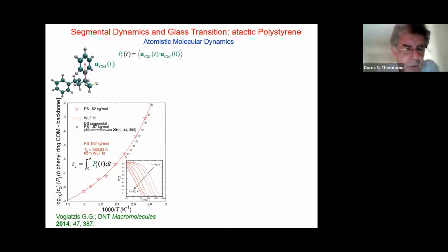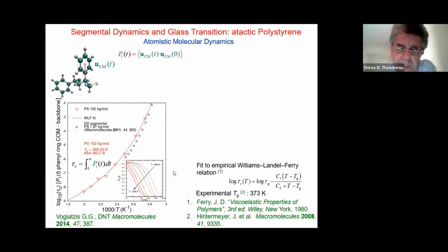Now, this kind of dependence, this nonlinear dependence, is very frequently described by a Williams-Landel-Ferry or a Vogel-Fulcher-Tammann expression relating the relaxation time with the temperature. So if one fits this line that comes out of the molecular dynamics simulation with this WLF relation, one can extract an estimate of the glass temperature, and here it is, roughly 380, which is not very bad when one compares it to the experimental one, which is 373.